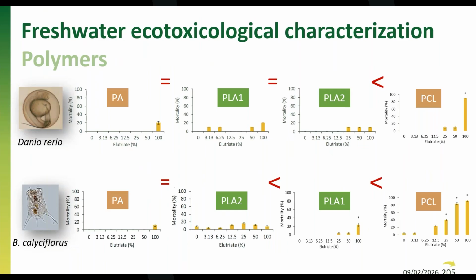And finally, as a final example, here I included some data regarding the polymers. So here we have two bio-based polymers, the PLA1 and 2 in green, and then the polyamide that is fossil-based and the polycaprolactone that is also fossil-based. And here I only presented the results for the fish and the rotifers because it's a lot of graphs, but for the other species, the pattern of results was similar. So here you can see that for the fish, the two bio-based polymers had no toxicity. For the fish as well, the fossil-based polyamide, but then PCL exerted some toxicity to the fish.